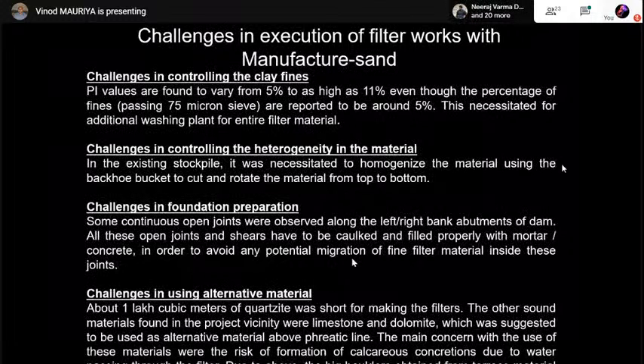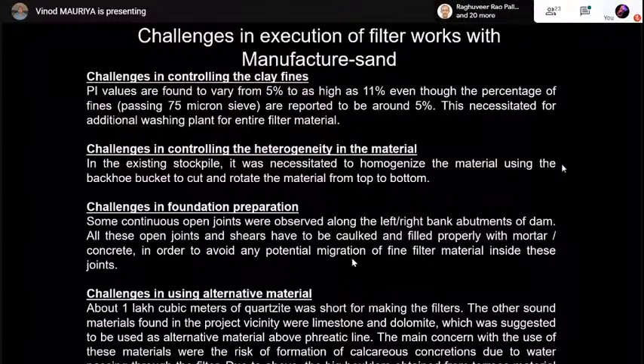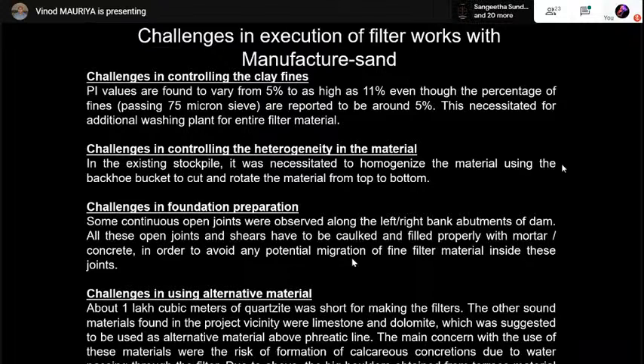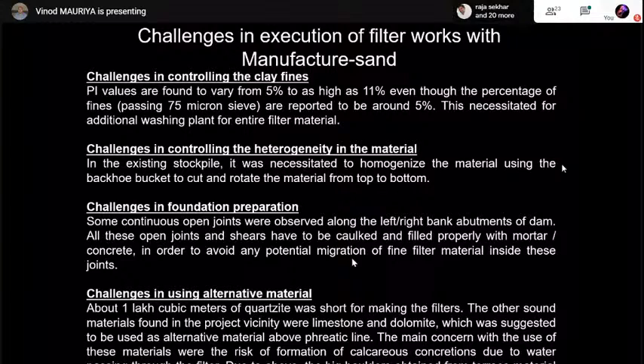Next challenge was in controlling the clay fines. Our requirement of PI values were 7 to 10. However, the PI values in this filter material were 5 to 11%, though percentage fines were less than 5% as per the requirement of our IS codes and international codes. But these PI values were very high, which were indicating that there is a percentage of clay which is not good for our filter material. So this necessitated an additional washing plant where we washed all the filter materials to remove this clay fines.